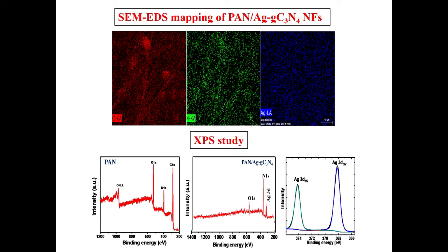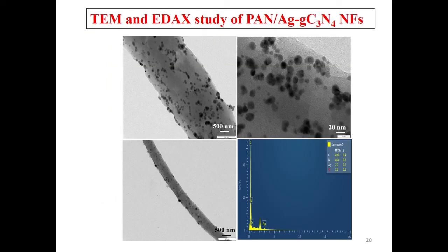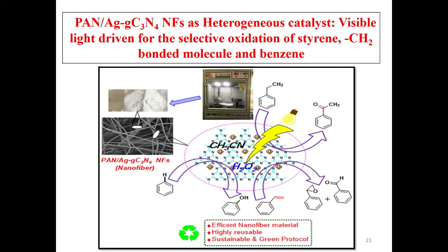The XPS study has also been done. XPS suggests that highly aligned nanofibers are found, shown by variation in the binding energy of that material. This is the transmission electron microscopy, where the Ag-gC3N4 nanoparticles are seen decorating the surface of the fibers, clearly observed from that study.